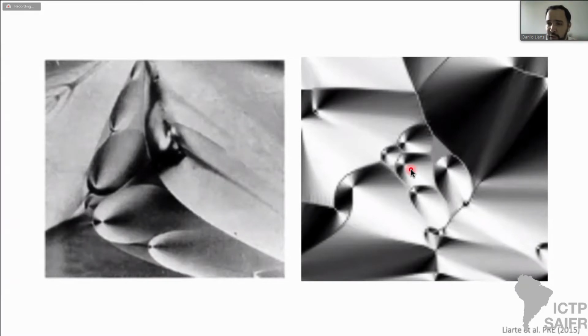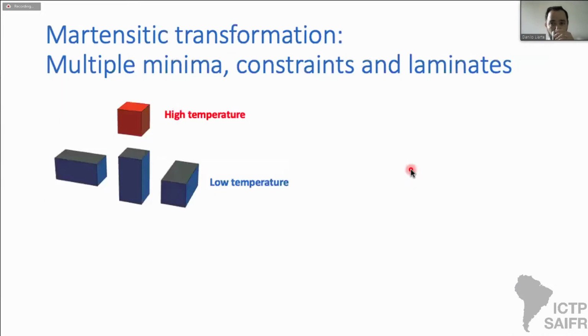Now there is another well-studied system in which coexisting low energy configurations merge, interpolate, and lead to non-trivial structures. They are called the Martensites. There are many kinds of Martensites, but let me remind you of the cubic to tetragonal transformation, which is easy to explain and visualize. In this example, the important idea is that there is a class of crystals whose cubic unit cell deforms into a tetragonal shape at low temperatures. As you can see, this deformation can take place along any of the three Cartesian directions.